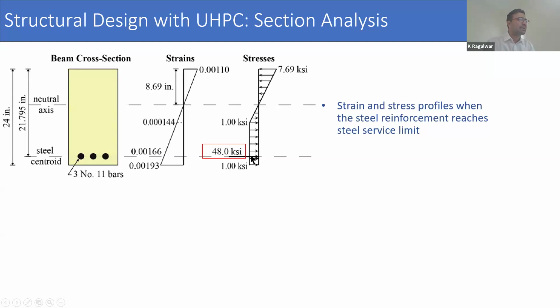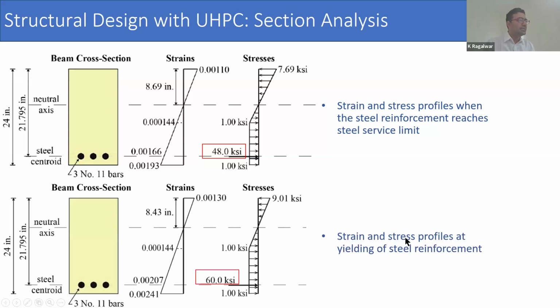So 48 KSI would give us some strain value in the steel, and that strain value in the steel is considered at this location, and a strain profile is built. Once we know the strain profile, we can calculate the stresses and again calculate what is the resulting moment. So the third point here would be yielding of reinforcement, and that's why we see from 48 KSI, we have increased the value in steel stress as 60 KSI, calculate equivalent strain here, determine the strain in extreme fiber on compression and tension side, use our model.